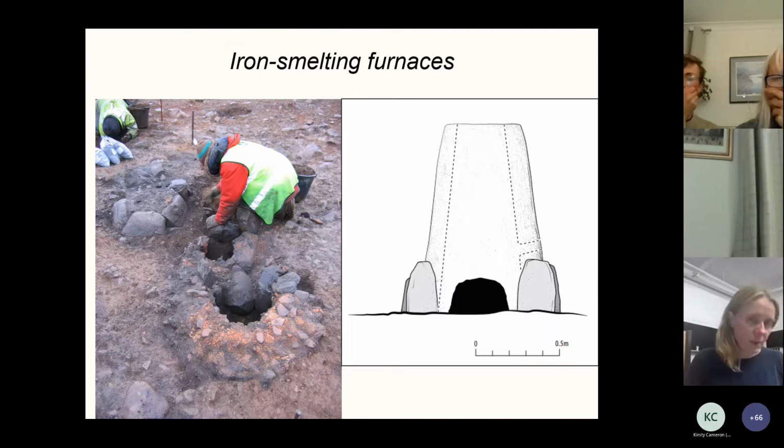The smelting furnaces were all freestanding, non-tapped furnaces that produce bloomery iron. To produce iron within a non-tapped smelting furnace, the fire is first started in the base of the furnace, the slag pit, with the ore and the charcoal placed into the shaft above. The ore and the charcoal would be heated together, and the slag would gradually form in the pit.